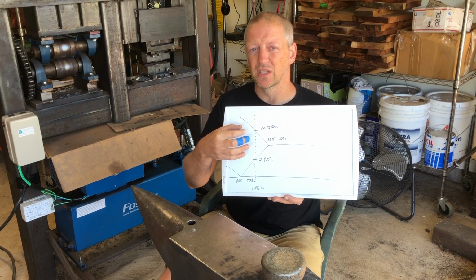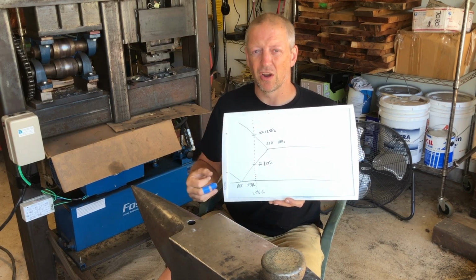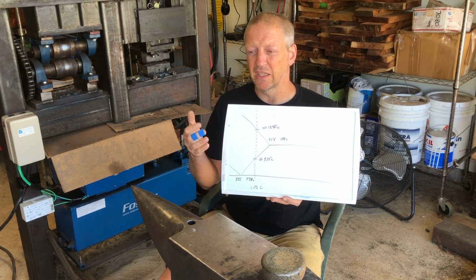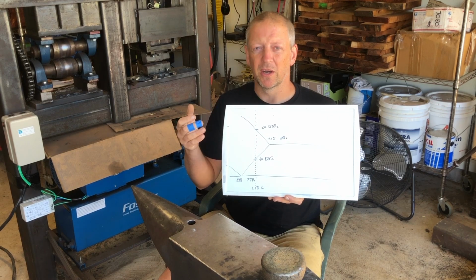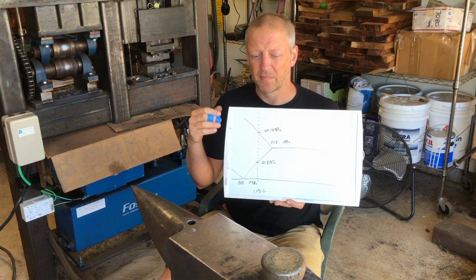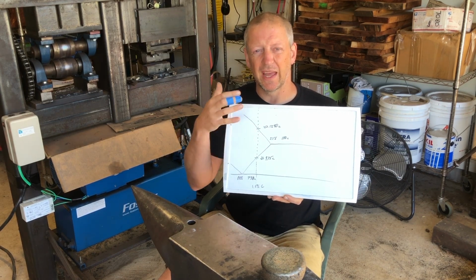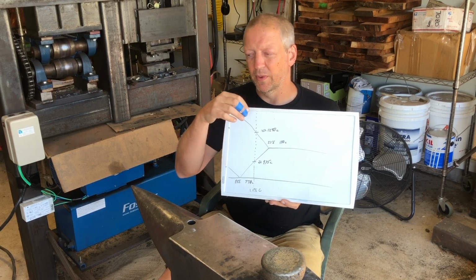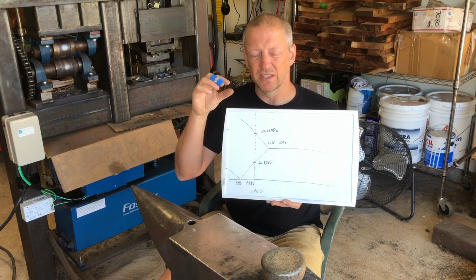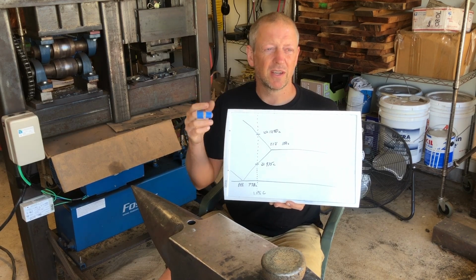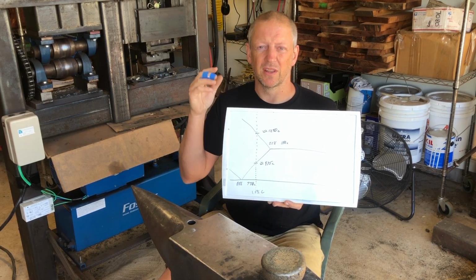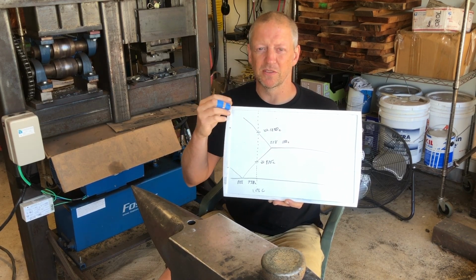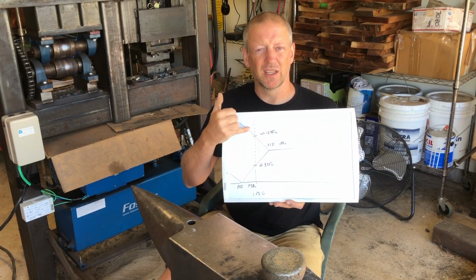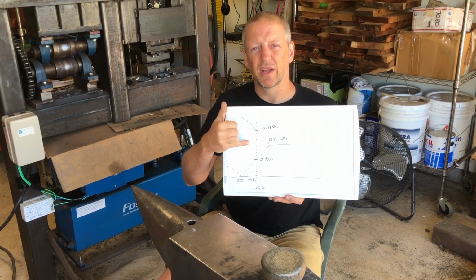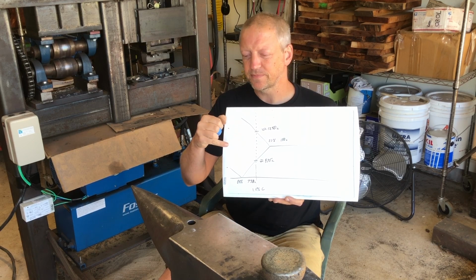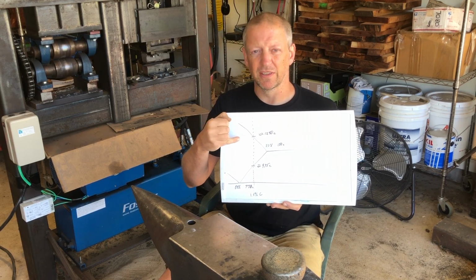And what that results in are very large, pretty blocky primary carbides. So if you etch that little window on the ingot and you get that very dendritic structure, very likely those are actually the primary carbides. Those carbides formed essentially during and right at solidification, or sort of full solidification.